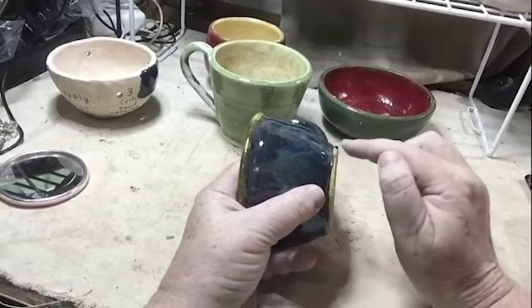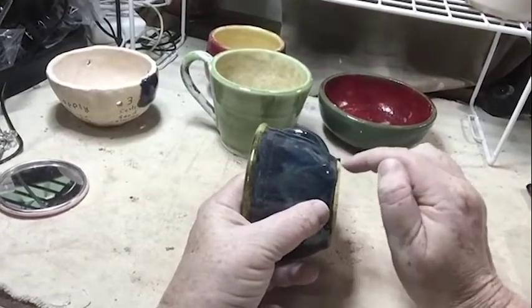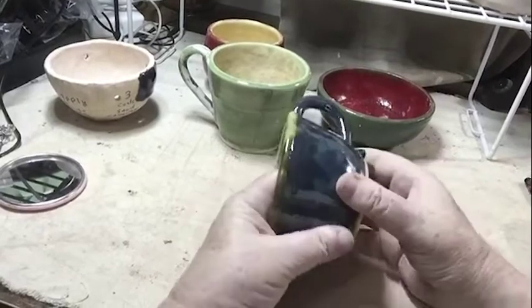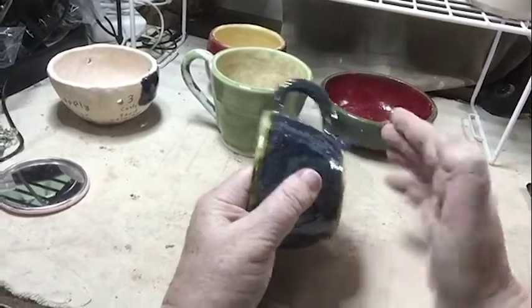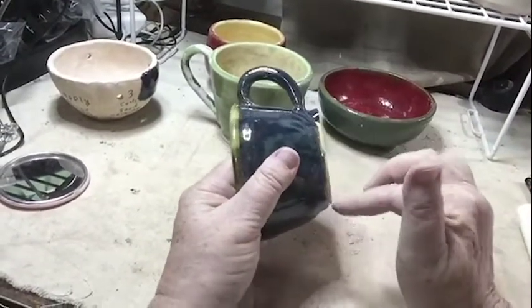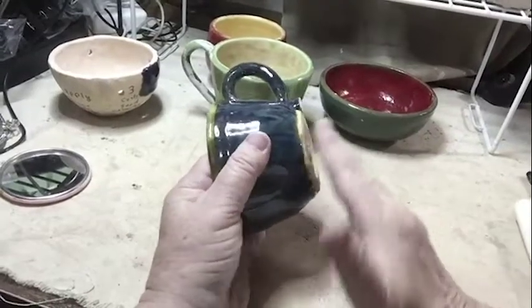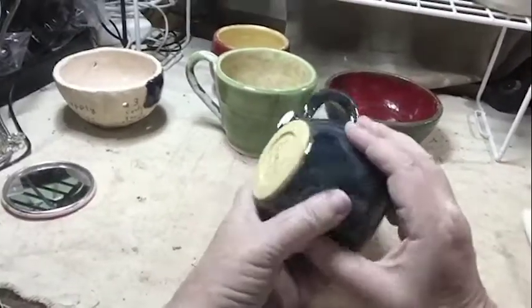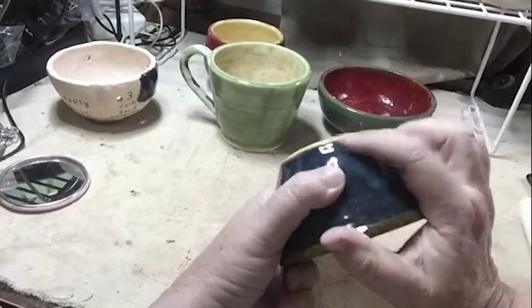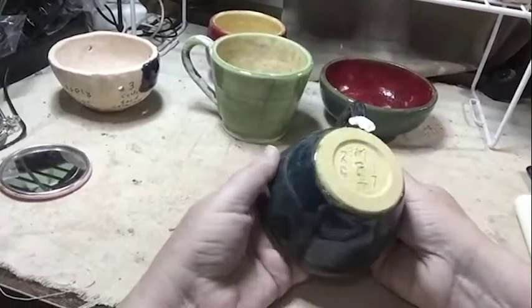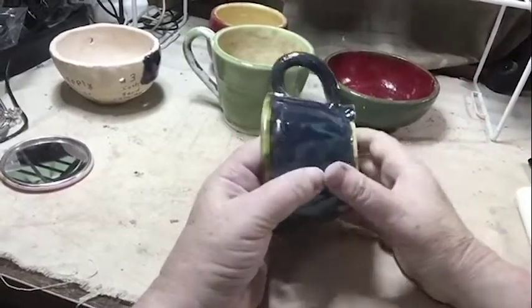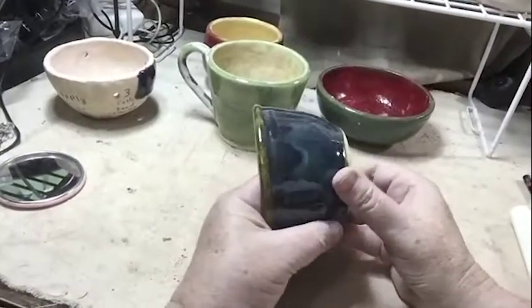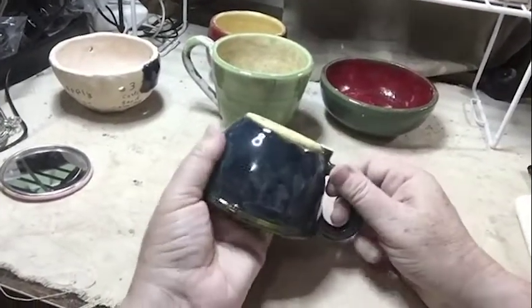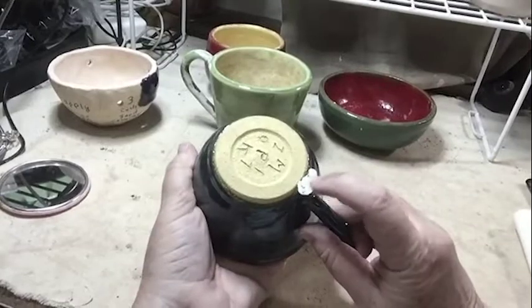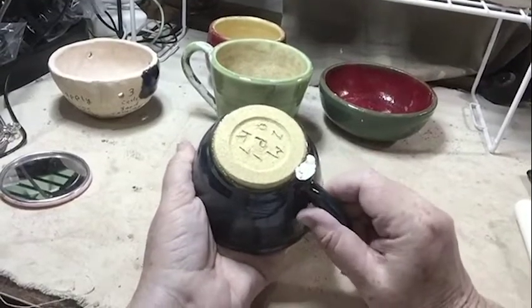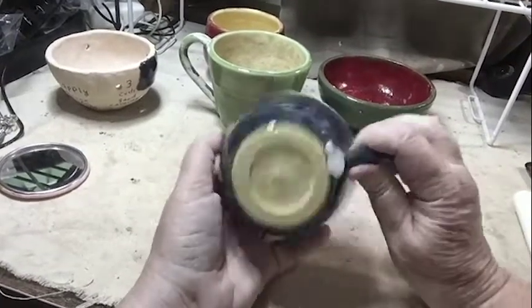So if we did that and our glaze ran, there would be no place for that glaze to compensate. It would run down just like this and all be caught right on the bottom of your piece there. It can run under your piece. But the worst is when it sticks to the kiln shelf and fuses to the kiln shelf, because often that means you have to break your piece off the kiln shelf, and that can damage the kiln shelf, and kiln shelves are very expensive. They are covered with this white coating that can help facilitate your piece breaking off.